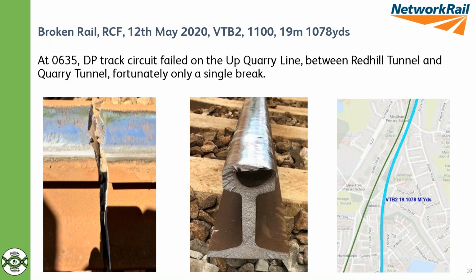And the final one I was going to show is more recent, this was this year, 12th of May. A failure there on the up quarry line between Red Hill and Quarry Tunnel. A few things we're still investigating further here. This was a premium rail steel, an HP grade rail, only 5 years old, with a very large transverse defect from rolling contact fatigue in the head of the rail. Fortunately, this just resulted in a single break. We didn't end up with a secondary break, but certainly the risk is high there because of the nature of RCF and the likelihood of similar defects in the vicinity greatly increases the chances of a secondary failure.